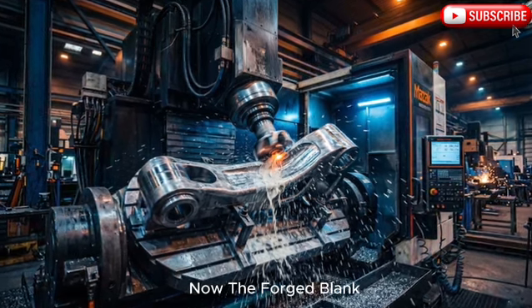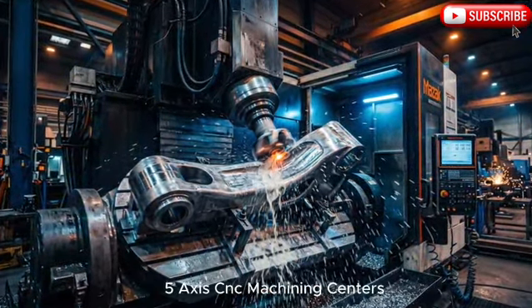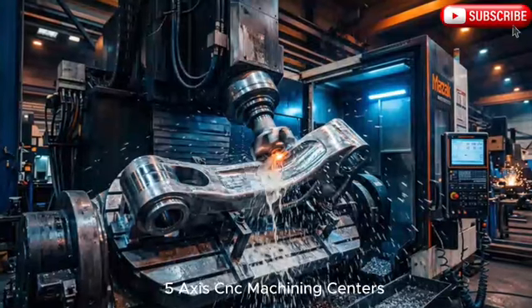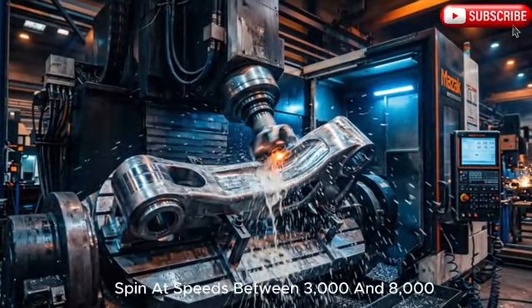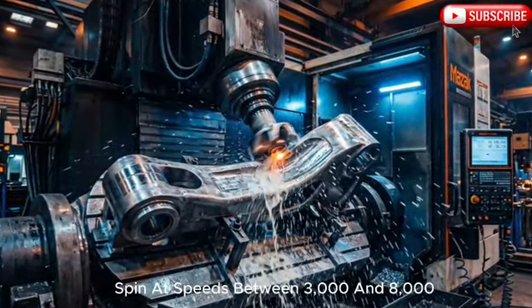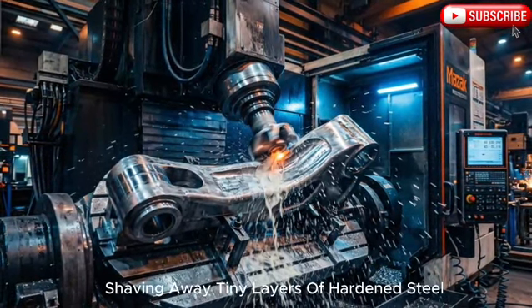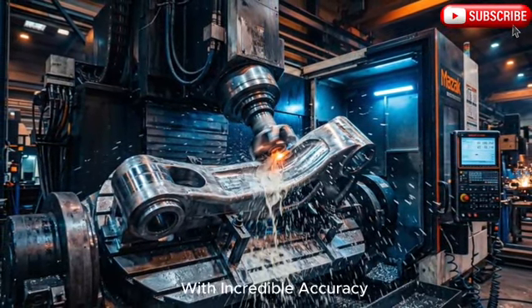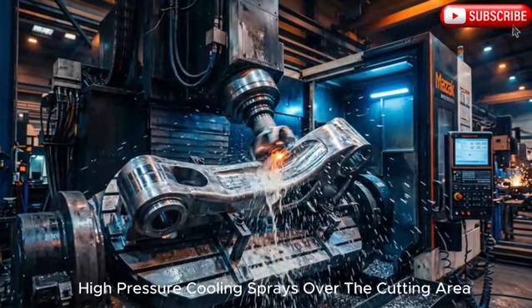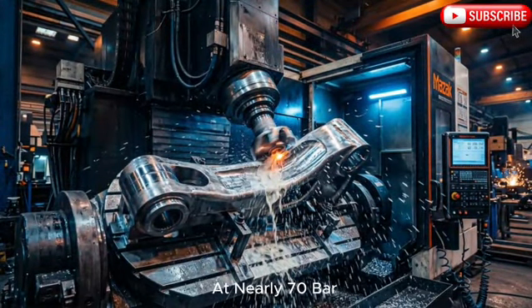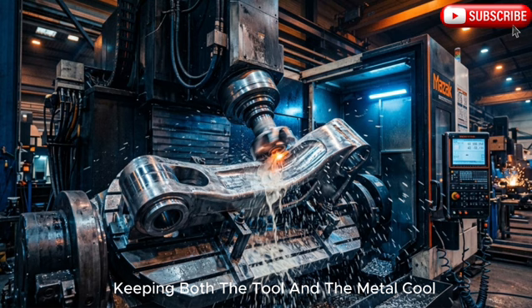Now, the forge blank enters one of the factory's most advanced 5-axis CNC machining centers. Diamond-coated cutting tools spin at speeds between 3,000 and 8,000 revolutions per minute, shaving away tiny layers of hardened steel with incredible accuracy. High-pressure coolant sprays over the cutting area at nearly 70 bar, keeping both the tool and the metal cool while carrying away glowing metal chips.